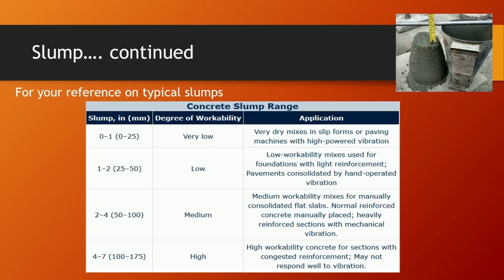Very dry mixes and slip forms or paving machines with high-powered vibrations use that. Slump, if you're going to have about 1 to 2, it's a lower slump, lower workability. The mix is used for foundations, light reinforcement paving, and hand-operated vibration. A slump 2 to 4, they say degree of workability is medium. Medium is for flat slabs, reinforced concrete, manually placed, heavily reinforced sections with mechanical vibration. That's typically what I see on most specs, is about a 2 to 4 slump.